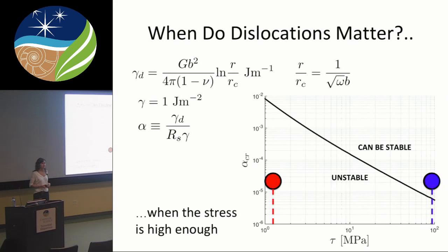Just a few words on what are the geological implications of some of this physics. So I mentioned to you that alpha is an important parameter, and that when we went through all the physics to derive the grain size distribution model, we saw that alpha is really just the ratio between energy associated with dislocations and energy associated with the grain boundary area. And if I take a typical material, say olivine, in this case just pure olivine, I have these parameters available, say for a given stress, what are going to be these energies. And I have that for the boundary and for the dislocation density with all these parameters.